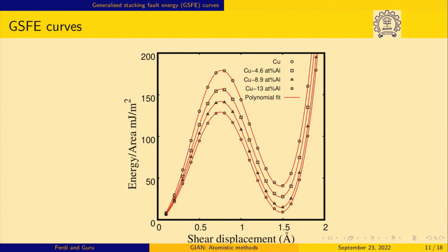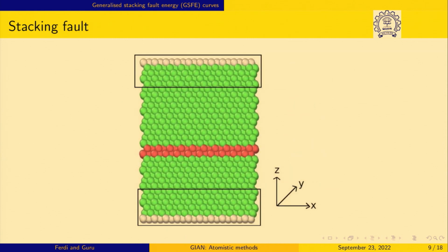Can you think of, if any of you do first principles also, you will know. So, the process is very simple. I generate a structure like this, which did not have a stacking fault, then I choose one particular plane and slide B atoms to C positions, 1, 1 bar 2 or some such vector I take, and I start moving it in that direction till it completes that vector, and then calculate potential energy at every point and then draw the curve. That is all I am doing.